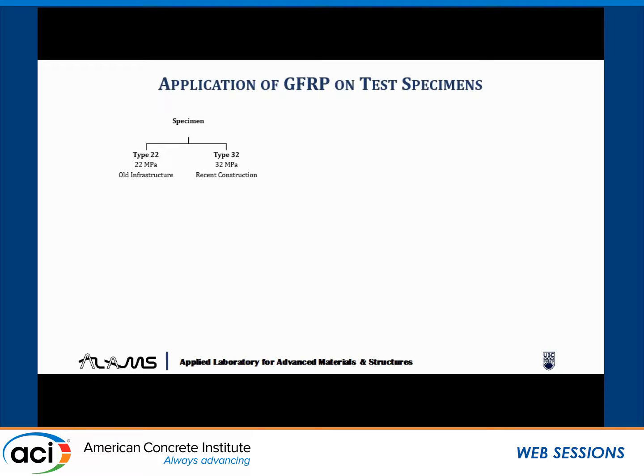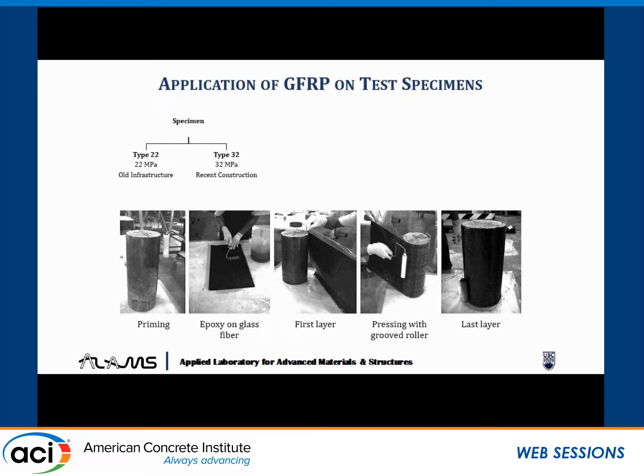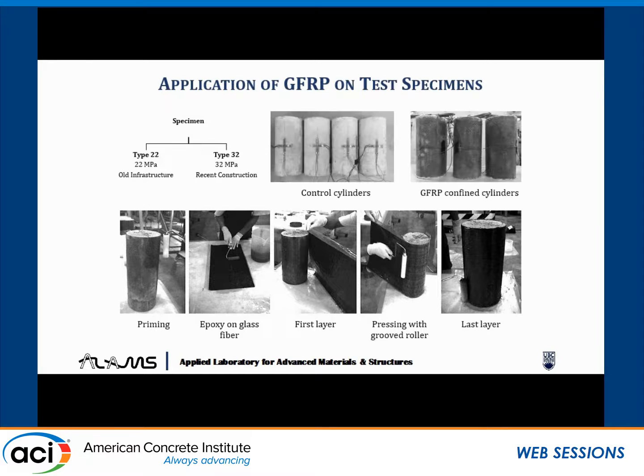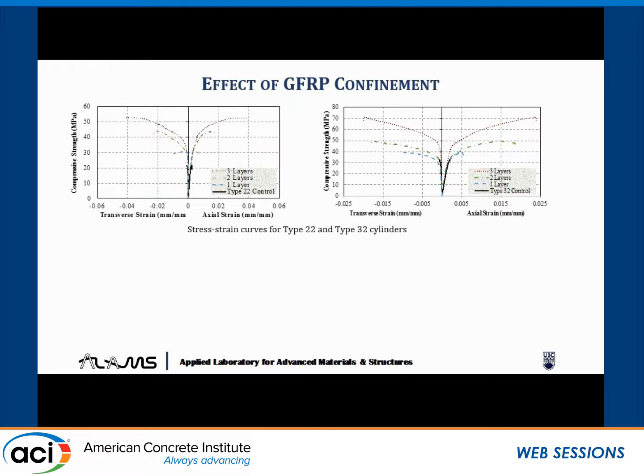Since we are talking about retrofitting or repairing, we are considering older types of concrete. In BC in particular, there are some bridges that have very low compressive strength, ranging from 22, and some also 32 MPa. So we wanted to see, for very low strength concrete, when you do the confinement with different layers of GFRP, how much improvement you can get. We tested with 1 layer, 2 layers, and 3 layers. This is the original concrete, 22 MPa, and with 1, 2, and 3 layers you get significant improvement in terms of capacity as well as ductility.